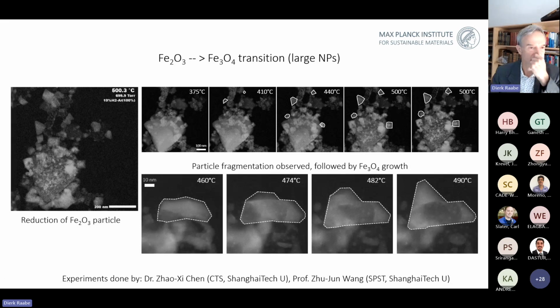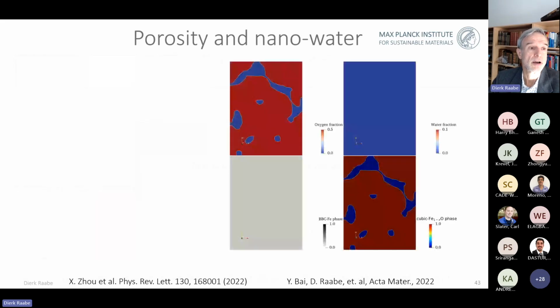And we study this also under these in situ conditions up to very high resolutions to better understand how, for instance, the nanovoids are formed and how they are percolating or connecting and so on, because we think understanding the kinetics of the connectivity of these pores as they are formed might play a very important role for the removal of the water. Why is that so important? Here you see a few tomographic nanoporosity analyses that we have done with tomographic electron microscopy to better understand how they are really connected.